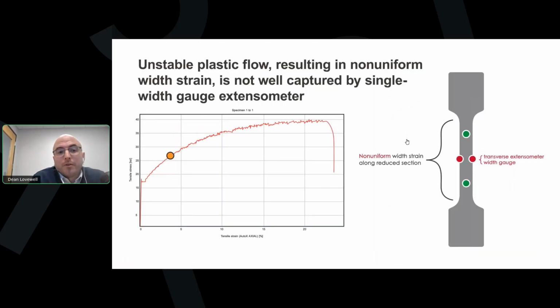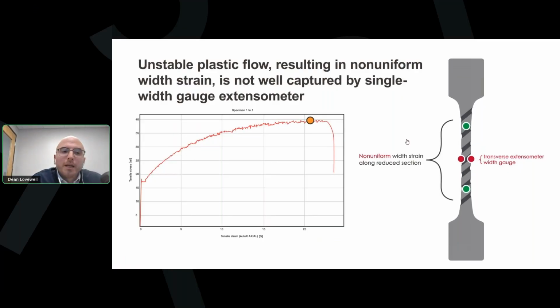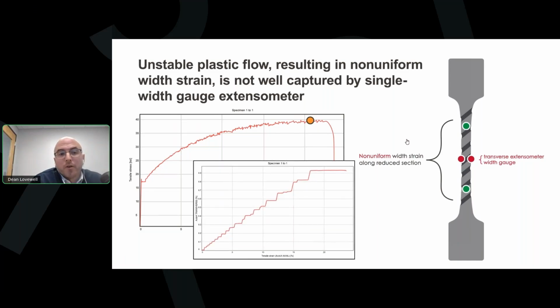This graphic demonstrates how this effect interferes with reliable plastic strain ratio determination. As the test proceeds through the strain hardening region, we see the pinning and unpinning in the sawtooth character of the stress strain plot. Each stress increase corresponds to the gradual pinning at dislocations, followed by a sudden decrease as they're released. Now, when we look at just the transverse strain data of this single width gauge extensometer, this is showing the strain that's observed in the width of the specimen.